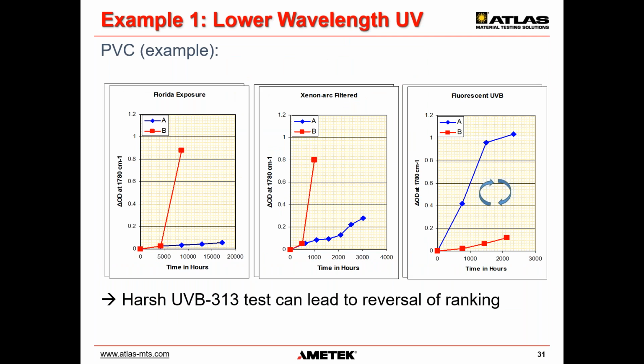So that you believe that, let's have a look at an example. In the graph on the left, the Florida exposure shows that material B, the red one, shows a greater change in optical density than material A in blue. And this same change was essentially replicated in properly filtered xenon arc. Here, it looks very similar, but look at the time. This is 20,000 hours, this is 4,000 hours.